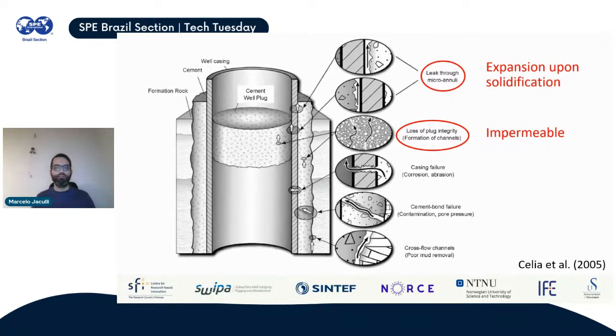You can have leakage through the microannuli. You have some gap between the plug and the pipe, and leakage could occur through this gap, since there are two surfaces that are touching but not necessarily closing the gap completely. Or you could have migration through the plug, which is a problem when you are using porous materials like cement, for example.